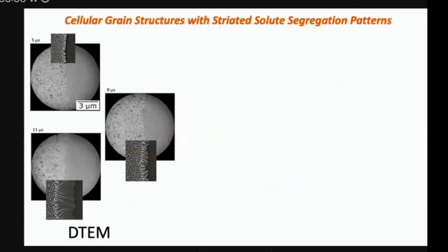And here's some results that come out. Here's a drop showing an interface. The main picture is the DTEM at different times shown at the top left. And the little insets are from our phase field simulation. And what you see is at the beginning, you have these bulbous little cellular structures that have just nucleated. They grow out and elongate a little bit.